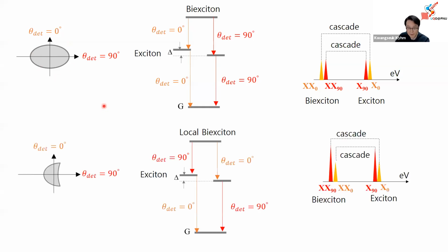But in our case, it's different because our coupled quantum dot structure consists of two droplets, but the two droplets are a little bit squeezed when the structure is formed. So the shape is something like that. It's not elliptical. So symmetry is further reduced. So it shows different selection rules. The 90 matches to the 0, not 90. So 0 matches to 90. So if you compare the exciton and biexciton emission pair, it's different.